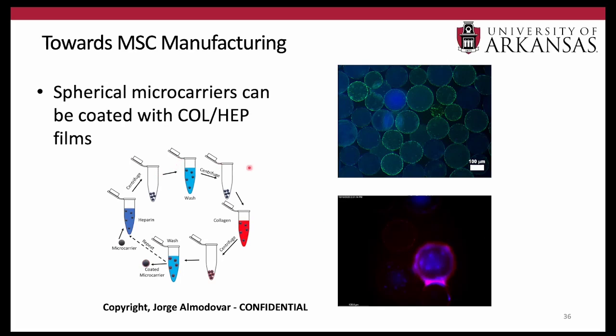We've developed different layer-by-layer coating techniques for these microbeads. One of them, for example, is this centrifuge-based assay where we suspend the beads in the polyelectrolyte solution, let it absorb for some time, centrifuge, remove it, rinse, centrifuge, remove, add the collagen, centrifuge, remove, and then rinse again, and you keep doing that over and over. That actually gives us some really nice coatings. Here in green is fluorescent collagen, and we saw really nice uniform coatings on these polystyrene beads shown in blue. The cells attach, and they like these coatings. So we're expanding this work more and more, moving into larger scale cultures.